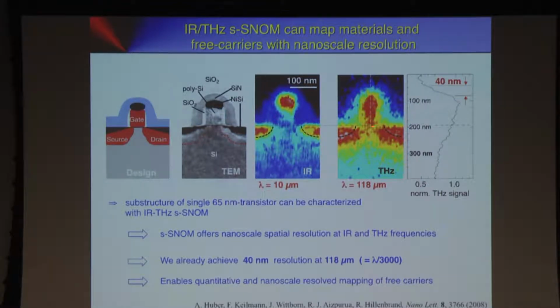Now this image, you may say, oh, this looks a little bit blurred. Resolution must be worse. No, this is not the case. You see these areas here, they are as bright as the metal. And the reason for that is that these are the red areas here. This is doped silicon. And it's so highly doped that silicon behaves metallic at terahertz frequencies, but it behaves dielectric at infrared frequencies. And this is because the carrier concentration is here in the range of 10^18 carriers per cubic centimeter.